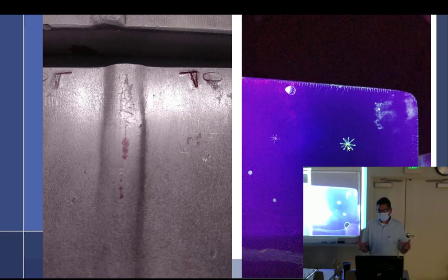They come with a calibration card and everything, so that part of your process control is that you actually put these in through the process in the morning, and you should get these star indications at the end of your process. If you're not, then either your water rinse is wrong or your materials are bad. So it's a way to make sure that you get an indication on the back end that you're supposed to be getting.